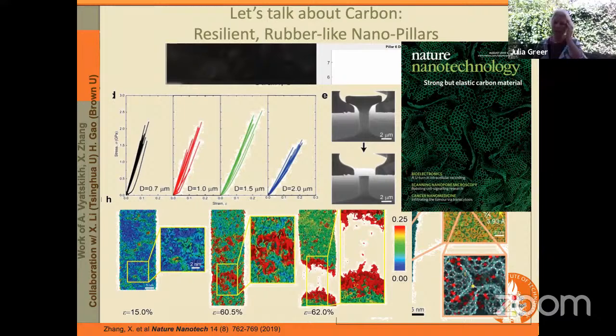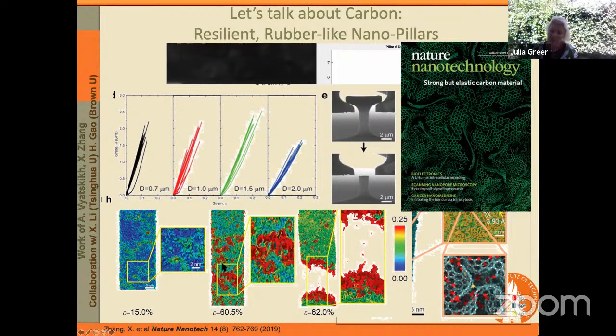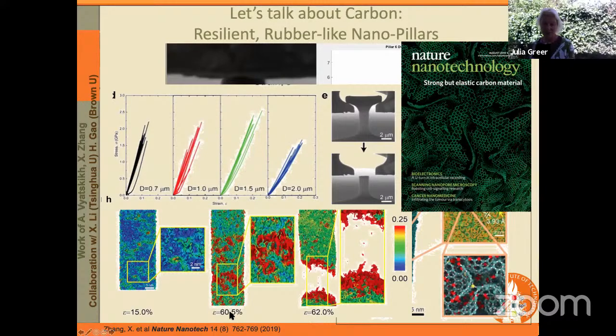Now, it turns out that in compression and tension, this behavior is prevalent in the sense that you can extend it up to 20% tensile strain. That is unprecedented in carbon, right? So it turns out that the answer really does lie in the presence of these regions. These very small regions with the curved graphene segments are able to undergo localized shear transformations such that they can collectively accommodate the application of the global strain. So you can see in the simulations here, for example, at a very high strain of 60%, you can see that they're extending quite substantially prior to failure here. So that's the explanation.